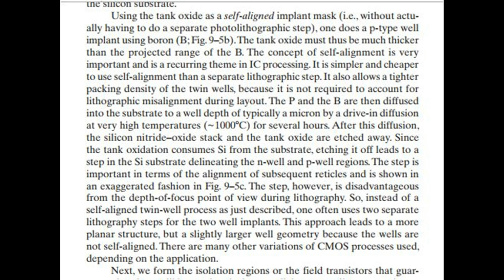After this diffusion, the silicon nitride oxide stack and the tank oxide are etched away. Since the tank oxidation consumes silicon from the substrate, etching it off leads to a step in the silicon substrate delineating the N-well and P-well regions. The step is important in terms of the alignment of subsequent reticles and is shown in an exaggerated fashion in Fig 9.5c. The step, however, is disadvantageous from the depth of focus point of view during lithography.